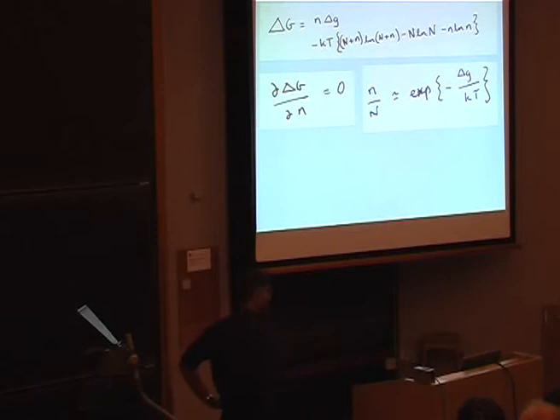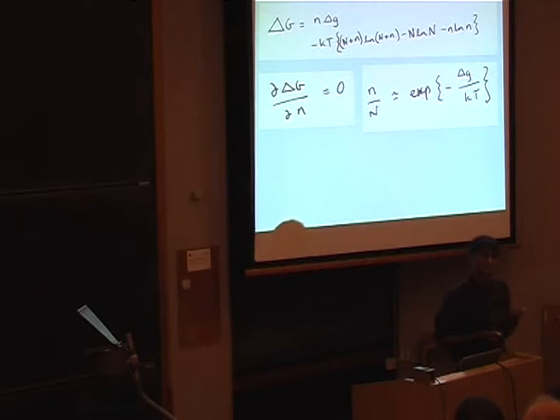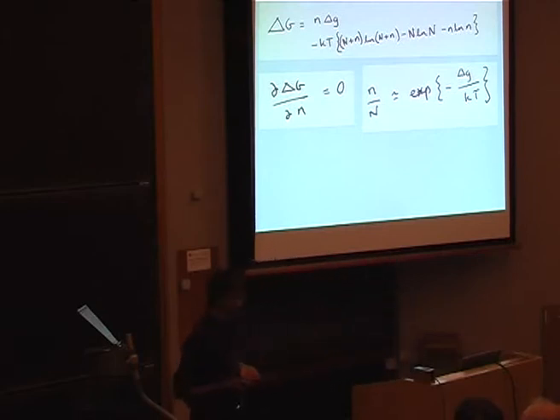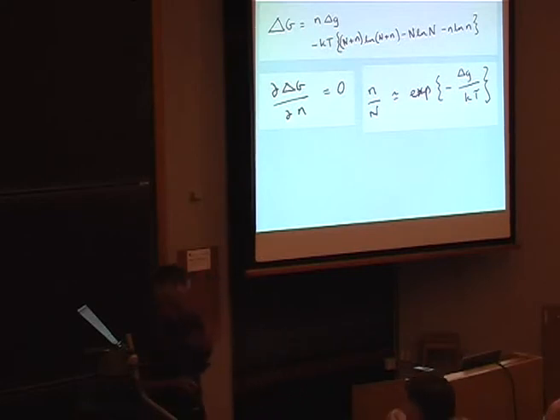Well, the first thing is that we need to remind all these people who are making these claims that there can be an equilibrium density of defects. Because look, this is an equation which we teach all undergraduates, that if you form n vacancies in the material and you multiply by the entropy of formation of that vacancy, that opposes the formation of the vacancy. But then by introducing a vacancy, you increase the configurational entropy, which favors the formation of the vacancy. So if you differentiate that, you end up with an equilibrium number of defects. That means it doesn't matter what you do to your material, they will exist there on average. So all materials will contain an equilibrium number of defects, and carbon nanotubes are no exceptions.